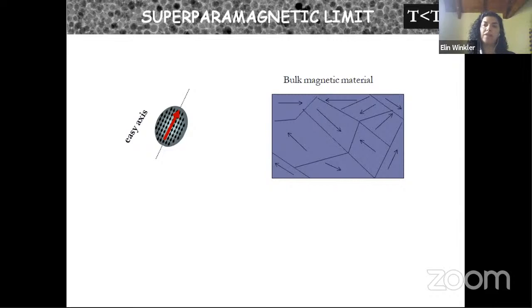What happens for the applications? All the time I require smaller and smaller dimensions, so we need to fabricate nanostructured materials. But when we reduce the size of a material to the nanometric scale, the system does not develop domain walls anymore because they have an energetic cost. So the magnetic nanoparticles behave as a single domain, which means that inside the nanoparticle, all the spins are aligned, okay? And the nanoparticle presents a huge magnetic moment that comes from the contribution of all the spins in the nanoparticle.